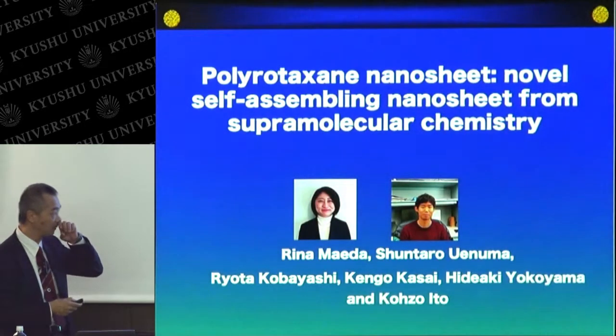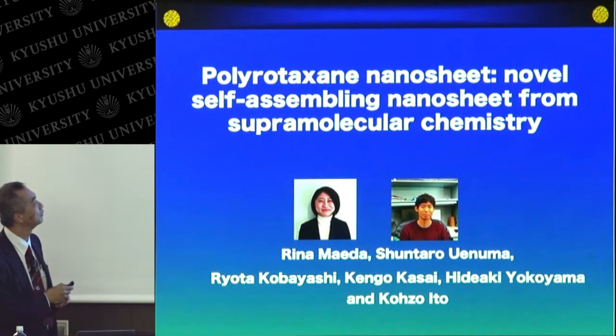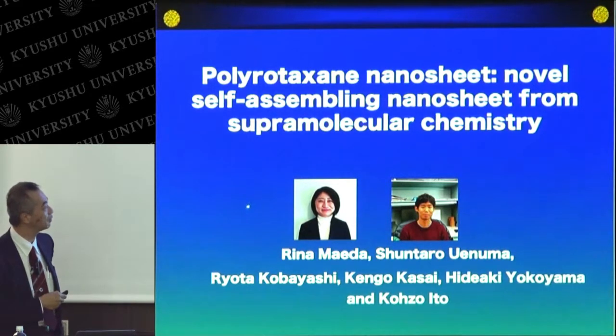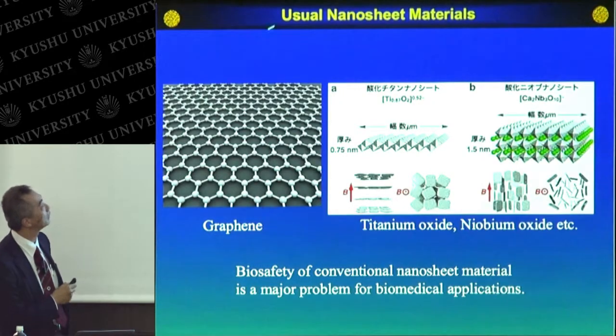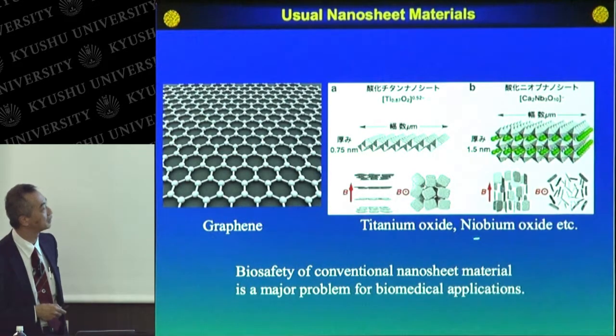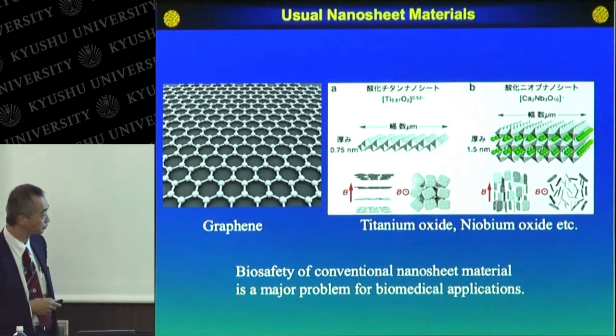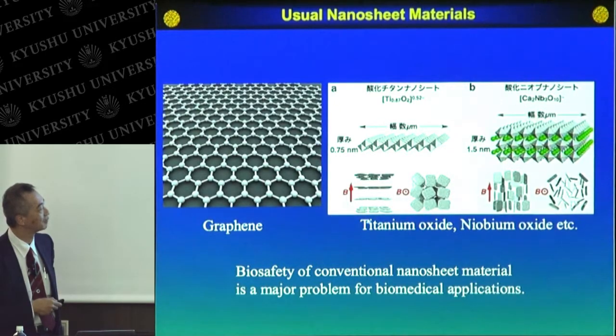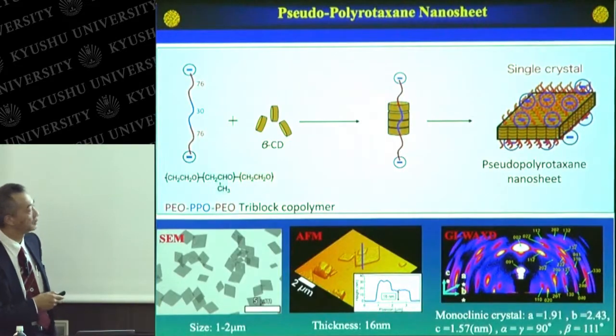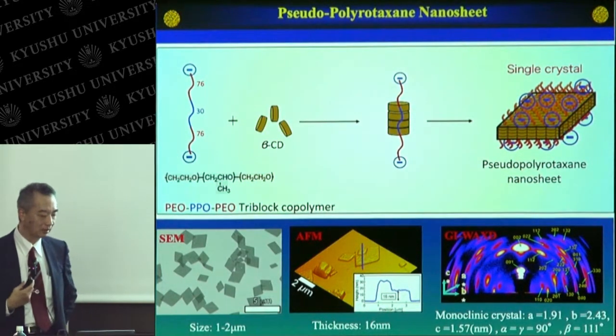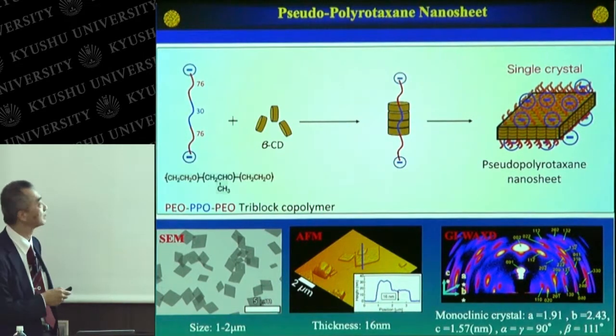Finally, I'd like to show you the very new results from my laboratory. We recently developed a pseudo-polyrotaxane nanosheet, a novel self-assembling nanosheet from supramolecular chemistry. This work was performed by Dr. Maeda and Mr. Uenuma in my laboratory. You know there are usual nanosheets such as graphene, titanium oxide, niobium oxide like this. And the biosafety of the conventional nanosheet material is a major problem for biomaterial application.